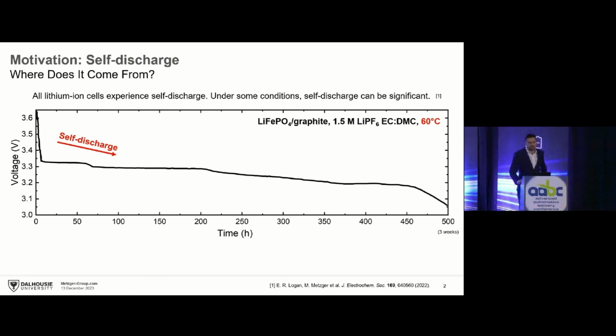And so here I show you an LFP graphite cell. It has a very standard electrolyte, 1.5 molar LiPF6 as the salt, and ethylene carbonate, dimethyl carbonate as the solvent. And we store this battery cell. It's a multi-layer pouch cell that we typically use in our laboratory. We store it at elevated temperature, 60 degrees C in this case.